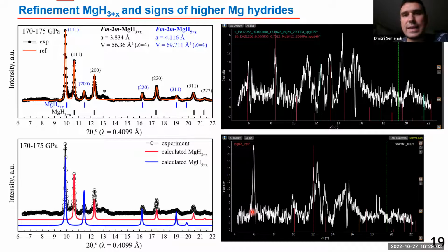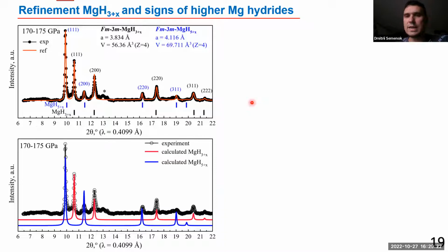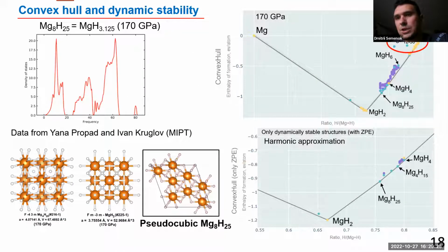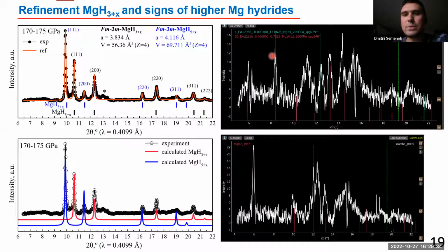I need to reanalyze this data and look at it again to compare it with theoretical predictions, because it seems like it's possible to explain those peaks by magnesium H12. Magnesium H12 is a tetragonal structure. And again, I would like to point out this region of the convex hull where we see a lot of stable structures with high hydrogen content. So it's possible that those two patterns or few patterns, maybe three, four, five patterns, exactly correspond to higher magnesium hydrides, probably molecular hydrides, which do not have superconducting properties, but have quite high hydrogen content.